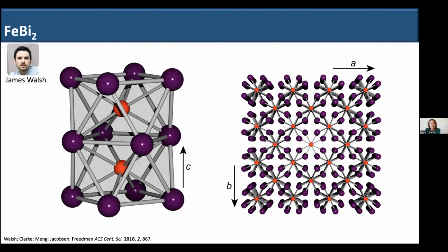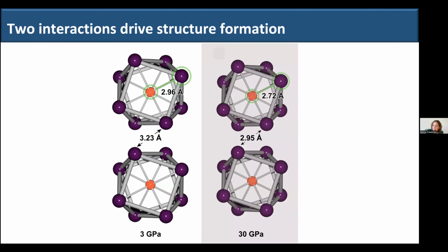There's James. This is the aluminum 2 copper structure type. And what you can see is that we have iron atoms that are directly bonded to bismuth atoms. This is arguably the first example of an iron bismuth bond in a solid state compound.